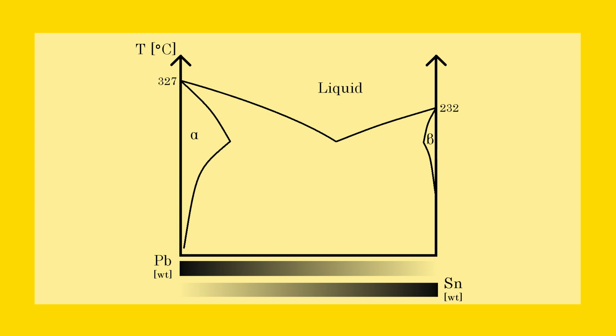It can also happen that the solid phase has to precipitate out from the liquid in small grains, making a mixture with the liquid. The temperature where these solid-liquid mixtures have to freeze is called the eutectic temperature. Here it is 183 degrees Celsius. I mean on the picture, not in my room. And below this we get some mixture of the two solid phases.